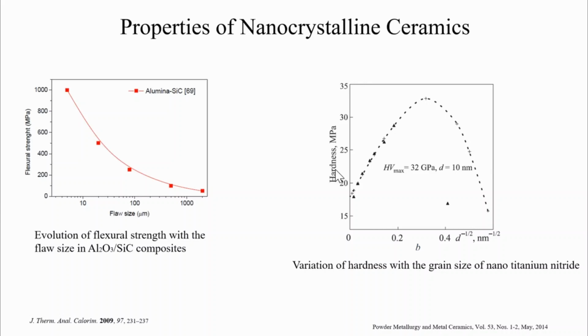The high strength observed in ceramic nanocomposites is not primarily attributed to an increase in toughness, but is likely due to a decrease in processing and contact-induced defect density, combined with an improved crack healing mechanism upon annealing. Transgranular fracture, often accompanied by reinforcement particles situated in grain boundaries, plays a crucial role in the strength enhancement. Furthermore, the enhanced creep resistance observed in these materials is linked to a grain boundary pinning mechanism. Investigations are ongoing to understand the mechanisms contributing to increased wear resistance as well.